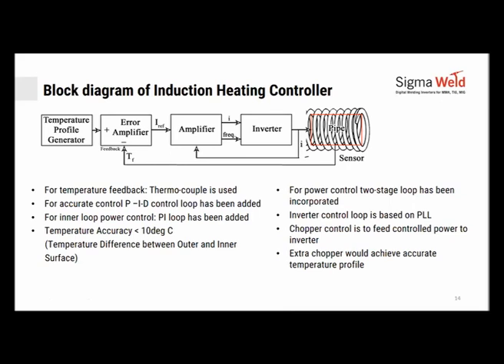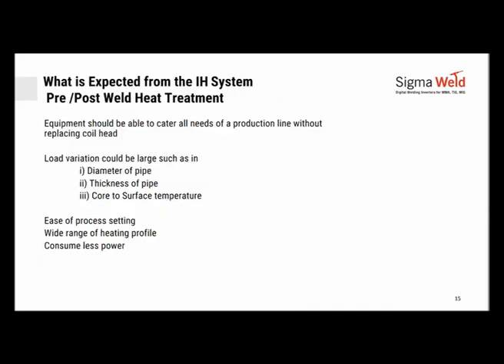We did certain experiments on plates and pipes as thick as 250 thick, and we have found that even over a period of time, the temperature difference keeps going down and is below 10 degrees. In smaller components or lower thicknesses, we can achieve a very good temperature gradient. For power control, a two-stage loop has been incorporated so that you have much better control. The inverter loop is in PLL. Chopper control is also available to invert. So there are a lot of controls on the power electronics side, which give you the accurate temperature profile that you wanted.